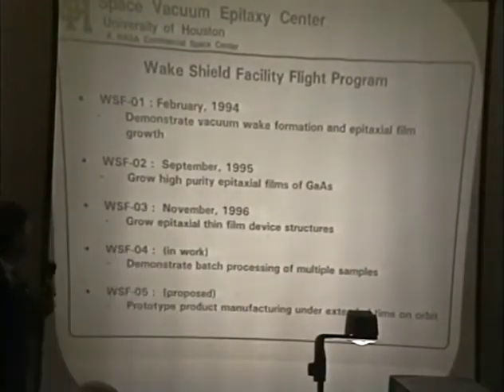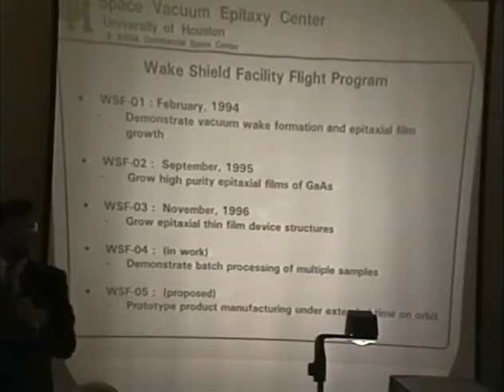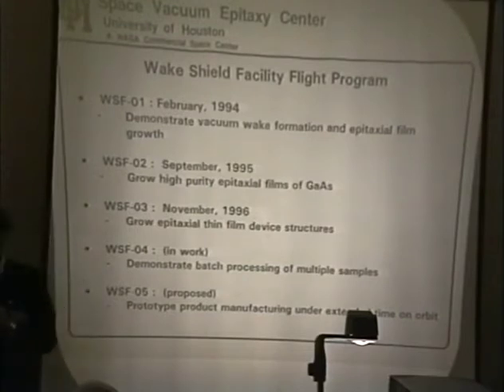Identified as a 4-flight program, we have now moved into a proposed 5-flight program. The first one was back in February of '94 in STS-60. It demonstrated the vacuum wake formation. We did identify wake formation, but also identified contamination of that wake due to the fact that we were on the arm of the orbiter, and we found the water vapor coming off the orbiter contaminating that environment.